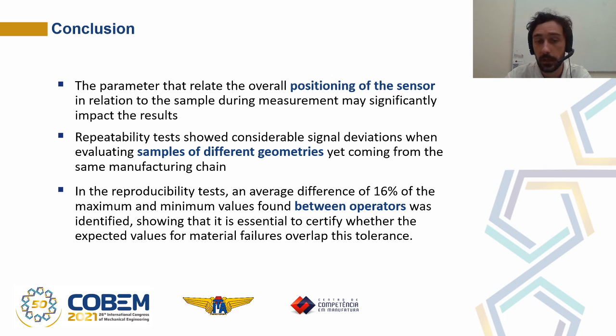Future work should propose the investigation of the Barkhausen noise signal combined with residual stress tests that will serve to demonstrate the signal difference found and perform a comparative analysis between parameters that influence the measurement with regions of metallurgical divergence that also influence the Barkhausen signal. It is expected that this study may allow future studies in the field of identification and investigation of gear failures using the Barkhausen noise technique. And for the continuation of this study, new parameters that can influence the measurements will be evaluated in order to contribute to the Barkhausen noise method for early failure detection in gears.